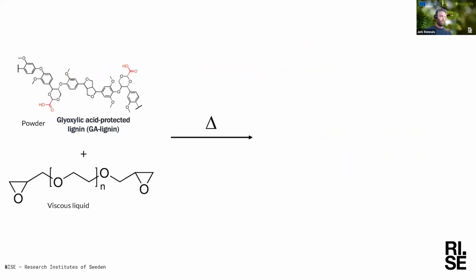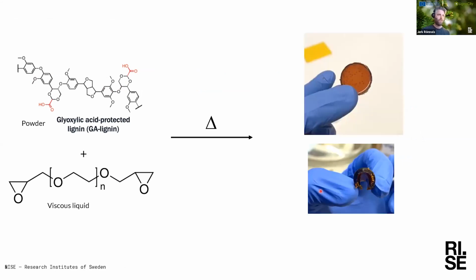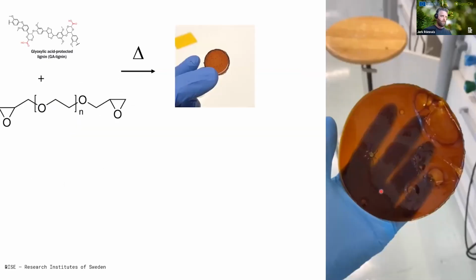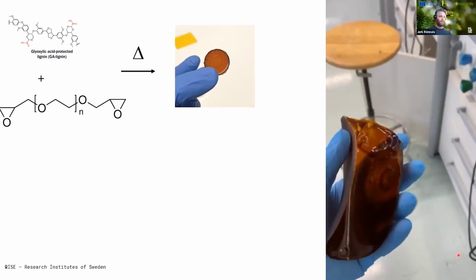And try out the reaction we did. So long story short, we mixed this lignin from Bloom, which is a powder, together with this PEG-D, the cross-linker with the tricky name, which is a very viscous liquid. We mixed this and heat it up, and what do we get? Well, more or less on the first shot, we got something very nice. We got a small little disc. You can see there's some air bubbles in it, but okay. And it's also flexible. It's bendable and stretchable, which is really nice. And here you can see a larger version of it, which is also, yeah, you can see how bendable it is.